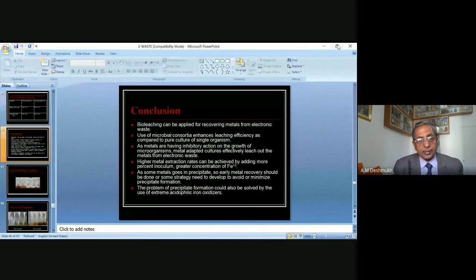And this is the conclusion that bioleaching can be applied for recovering metals from electronic waste. So bioleaching is the best process. Use of microbial consortia enhances leaching efficiency, meaning that microorganisms enhance the leaching efficiency as compared to pure culture. So we observe the consortia is better. A single culture organism is not better. Then as metals have an inhibitory action on the growth of microorganisms, a metal adapted culture should be used. So first of all, you have to isolate metal tolerant cultures.